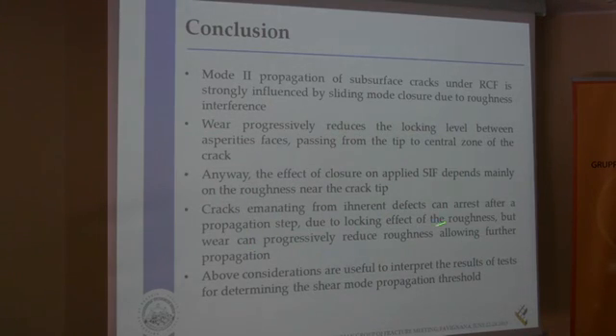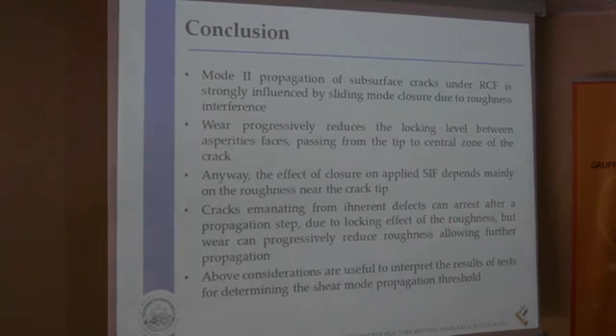And cracks emanating from inherent defects can arrest after a propagation step due to the locking effect of the roughness, but wear can progressively reduce roughness, allowing further propagation. So all this evidence can be very useful to interpret the results of tests for determining the shear mode propagation threshold, which is a very complex topic.